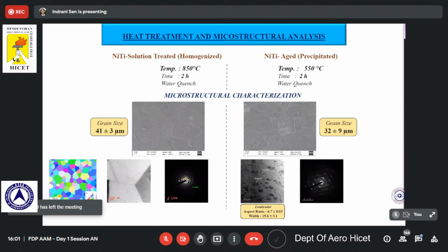Residual stresses in SMA during and after additive manufacturing. This is a very good question. Of course, there are residual stresses, and we also study the effect of residual stresses. In most cases they act detrimentally, especially when we are talking about pseudoelastic recoverability. So these residual stresses can be harmful, and we need to homogenize the component or structure to get rid of them. Again, residual stress can be good if it is compressive, especially for fracture and fatigue kinds of application. Compressive residual stress is good news. But if we have tensile residual stress, we need to minimize that.